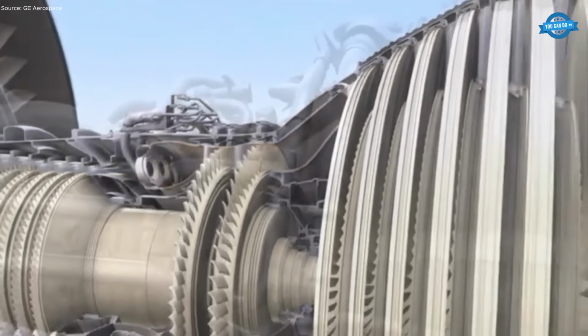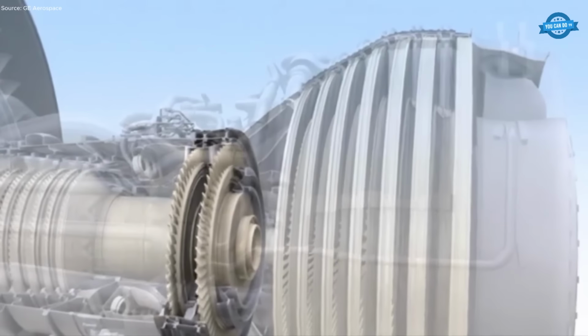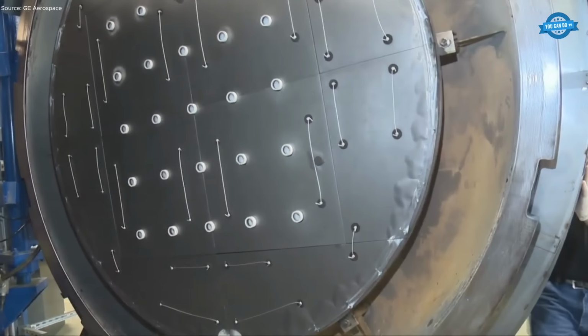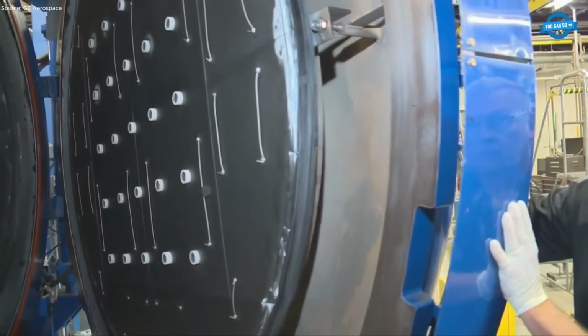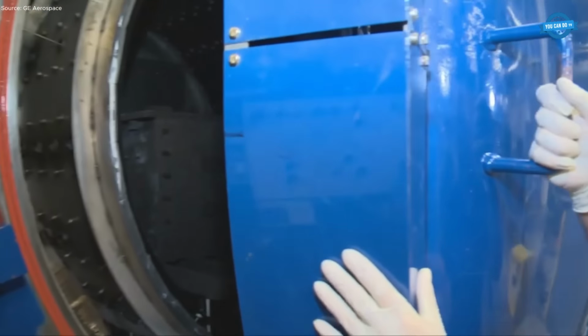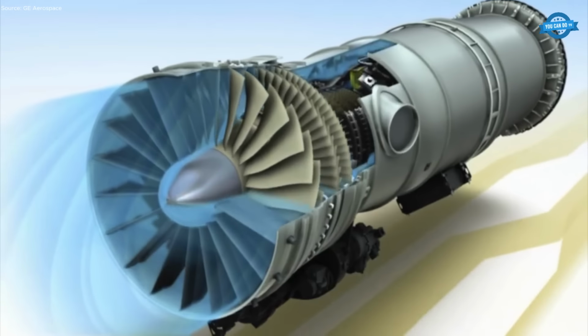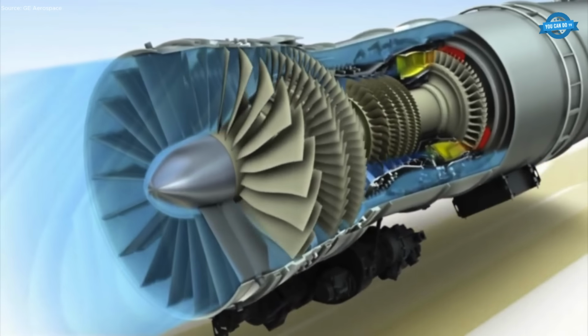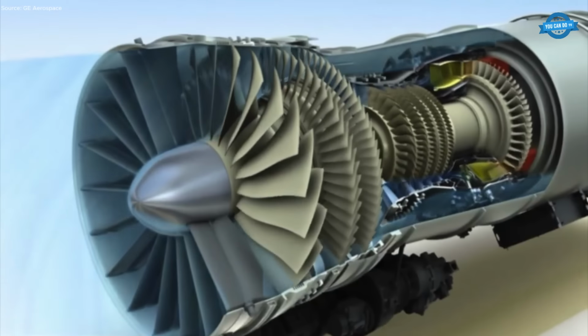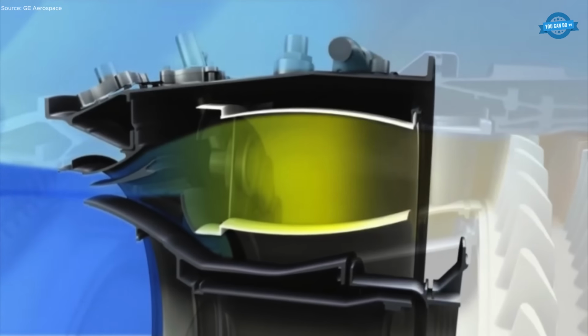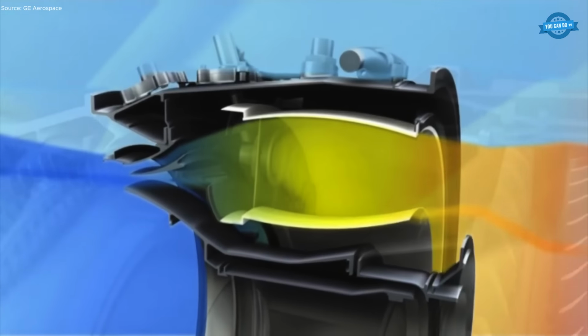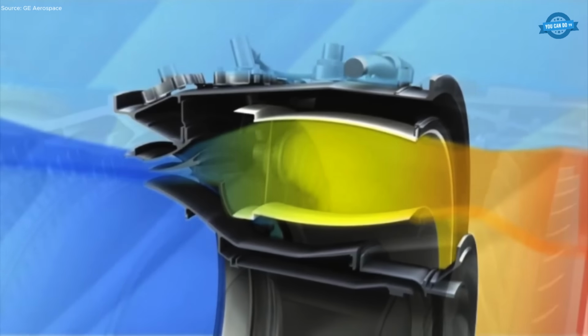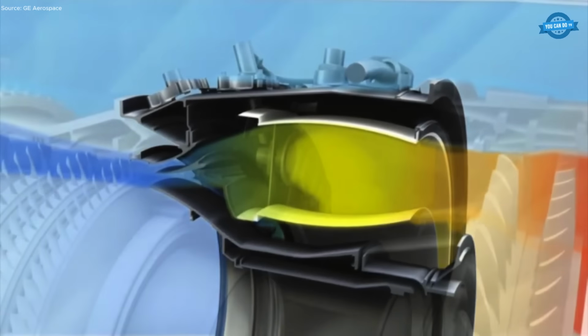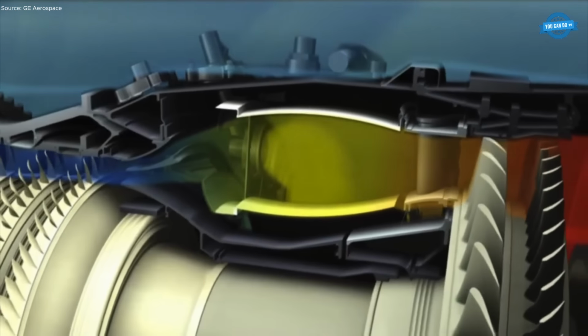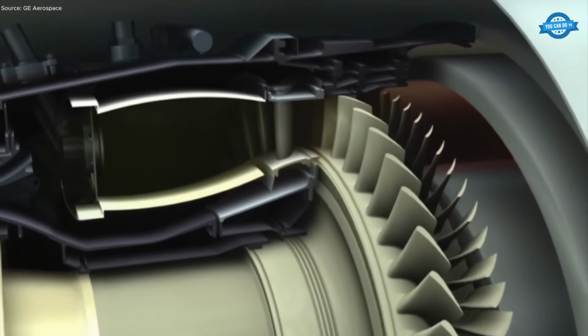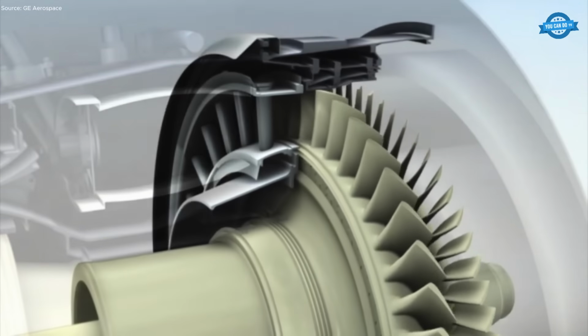After densification, components undergo precision machining with diamond tooling and receive environmental barrier coatings (EBCs) to protect against oxidation and corrosive species at extreme temperatures. Joining and integration to metallic structures requires specially designed interfaces and seals to accommodate differences in thermal expansion and stiffness. Quality assurance relies on NDE methods, ultrasonic inspection, X-ray CT scanning, and microstructural sampling to verify porosity, fiber alignment, and interface integrity.